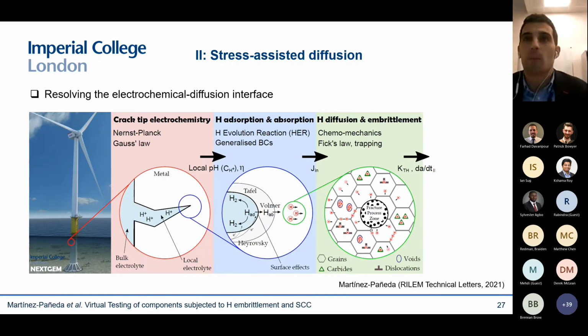And there's one last thing I want to say in regards to the chemistry. All these models rely on a boundary condition that is related to the hydrogen concentration. So we need to tell the model how much hydrogen we have in the crack surface. And this is easy to do when you have hydrogen gas, because you can use Sievert's law, and then you can come up with an expression that relates the hydrogen concentration in the crack surface with the hydrogen pressure. But when you are in aqueous electrolytes, then you need to resolve the electrochemical diffusion interface. And this is some of the work that we're doing now.